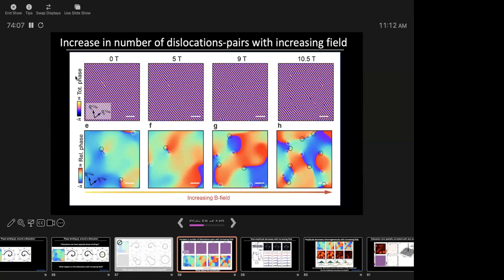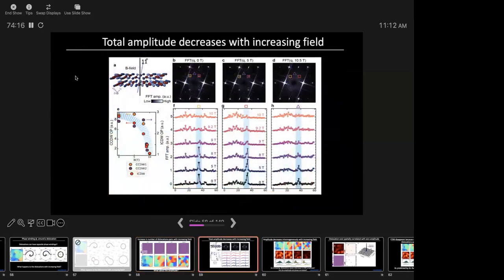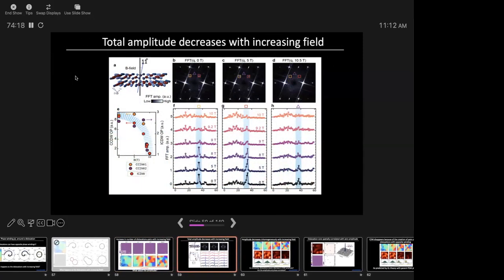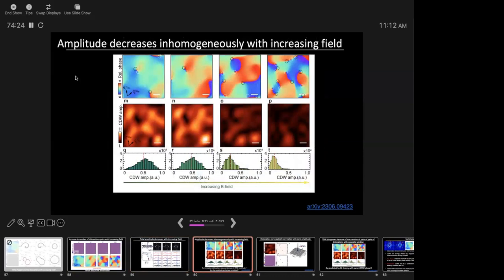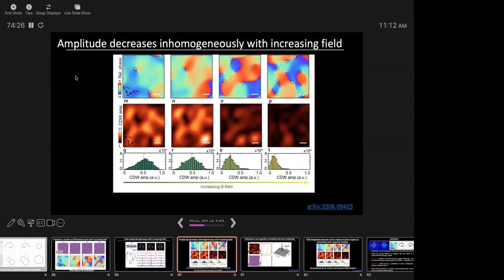The question you must ask is, what is the proof that it's these dislocations that are actually killing the charge density wave? And we can actually check that. So we know that the amplitude dies as a function of magnetic field, but now we can plot the amplitude in real space as a function of location. So here is a plot of the amplitude as a function of location. These are amplitude maps. These are the relative phase maps.